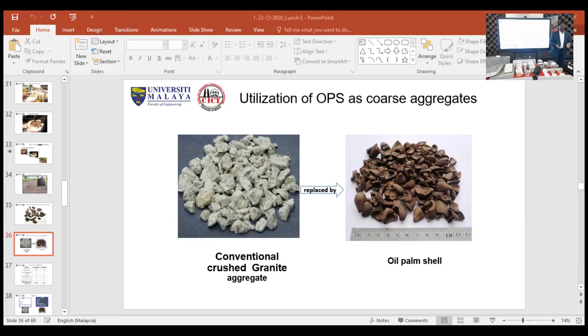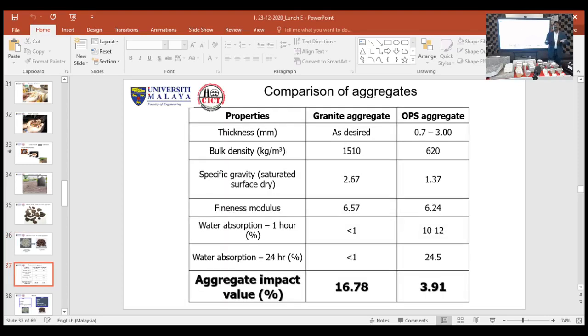And the properties you can see. For the conventional aggregates, the bulk density is 1500 kg per meter cube, whereas for this oil palm shell it's actually less than half, 600 plus. At the same time, if you look at the bottom one, that's the aggregate impact value, that was the key factor for us to investigate this further. Because when we hammer the conventional normal weight aggregates, the impact value is quite high, 16.78. Whereas when we hammer this oil palm shell, which has a lot of fibers inside, it doesn't crumble, but rather it has energy absorption characteristics.